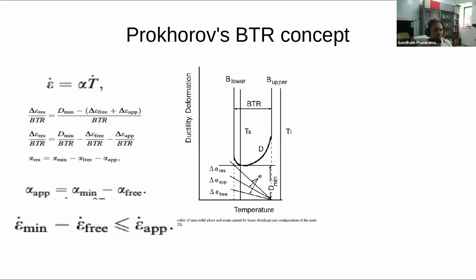The Prokhorov BTR concept says that there is a temperature range where ductility is not available, and therefore the shrinkage cannot continue at the rate you are imposing, and then it will crack. Such measurements are now possible in Gleeble, so Prokhorov's BTR concept can be expanded to Gleeble tests today, and we can characterize the crack susceptibility quite well by experimental measurements itself.